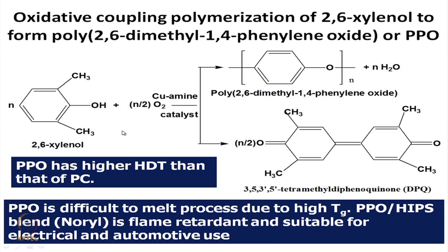It is prepared by oxidative coupling polymerization of 2,6-xylenol in presence of copper amine as catalyst.